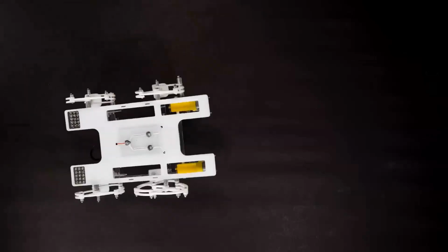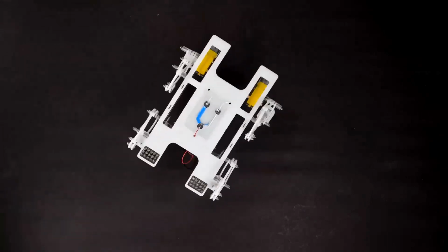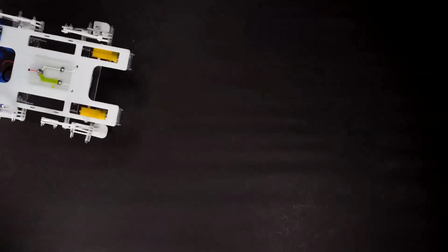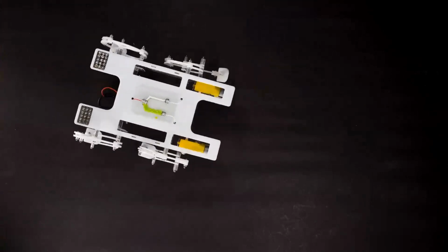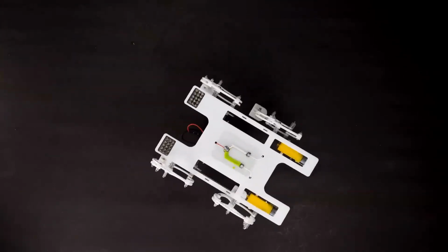And so this is in the partially dehydrated state. So both of these are electrically conductive, so current is being delivered to both sides of the robot, to the motors. And now when we rehydrate the left, you'll see we use a blue dye there just so you can see where we're breaking up that network. You see now the motors on the left are a little bit slower, right? The reason this is significant is not just that we're showing this programmability, but also the fact that the conductivity of this gel is so high, we can actually use it to deliver current to these motors. So again, this is also something that will just be infeasible with just ionically conductive gels.